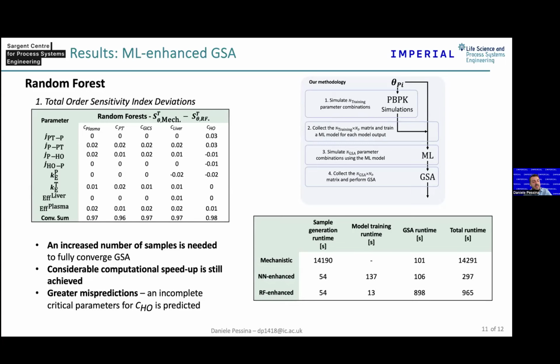And actually, we missed a single critical parameter for one of the outputs with this methodology. However, I think it's important to also note that that parameter was on the boundary of being called non-critical. So any kind of misprediction would have made it non-critical, and I think any amount of engineering judgment would have just told you it's close enough to being critical. And in terms of the runtime, again, the random forest, including the training, which is quite short anyways, took 965 seconds. So that's around 16 minutes of computation. So again, the neural network was 5 minutes, random forest was 16, and the mechanistic model, so the standard method, took 4 hours. So a massive increase in computational speed up.